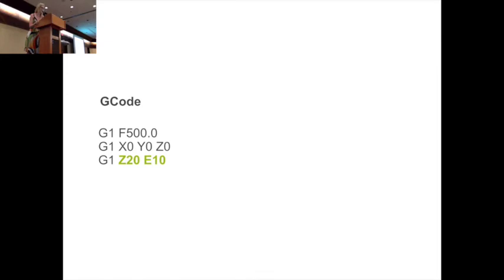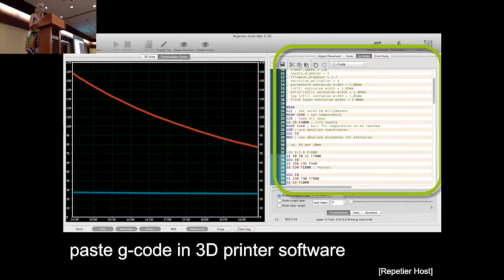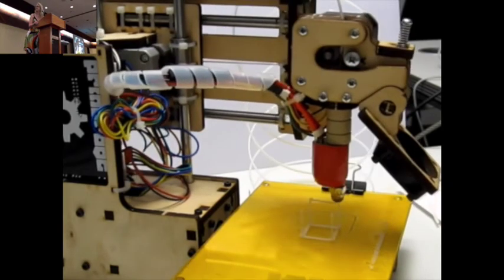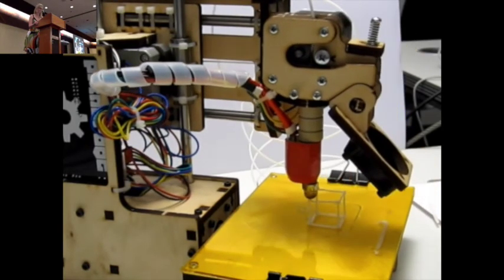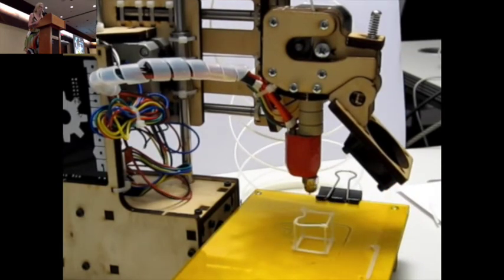To test this at home, you only have to set the print head speed, then move the print head to the origin, and from there you can move the print head up and extrude material all the way. And that's it basically. All I need is to paste these lines into your 3D printing software and execute them. So here's the little cube test we did in the first weeks. As you can see it kind of works, but the edges really do not look good here. They are not really straight, there's too much material extruded, the material also sags along. So there's definitely space for improvement.